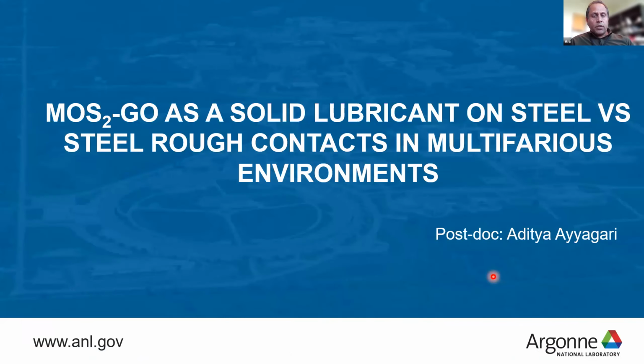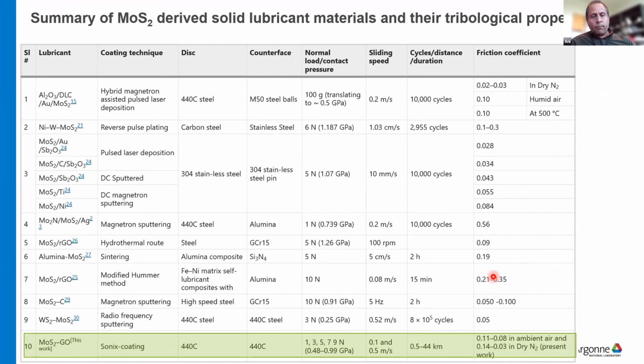So in this case, we worked with another solid lubricant, which is molybdenum disulfide, and then we combined it with graphene oxide, and I'll explain why exactly we do that. So MoS2 tribologically, again, just like graphite, is known from many, many years as a solid lubricant. But sulfur is one of the problems there. Sulfur always interacts with the atmosphere, grabs the oxygen, and that's how degradation of the MoS2 happens, with the formation of molybdenum trioxide.